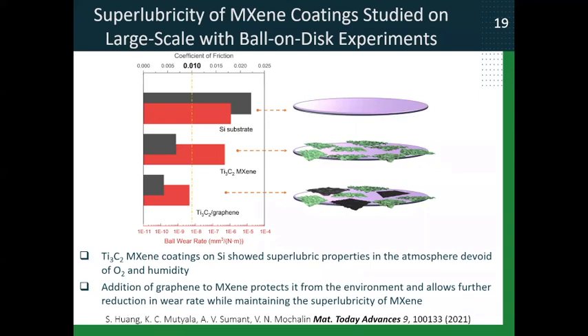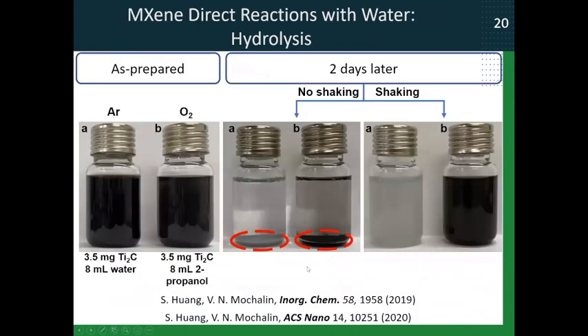Now, when I say protected, what do I mean? Well, this brings us back to understanding why MXene did not demonstrate superlubric behavior in just ambient atmosphere, because we hypothesized that MXene may actually react with humidity and air in the environment. Over the past few years, we looked extensively into the chemistry of these interactions, and it turns out that yes, MXene does react directly with water, which we call hydrolysis, and it also can be oxidized by air. This is another big part of research activities in my group, which I am not going to cover, but if you are interested, just go and read these papers.